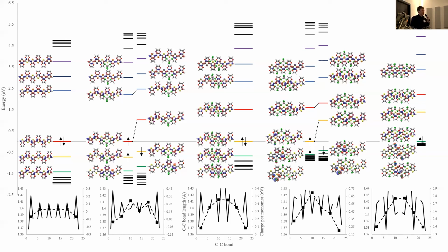Now, when you introduce the anion, it does indeed introduce an anti-bonding and a bonding state. But what this shows is that actually that's not driven by the anionic anti-bonding bonding state. In fact, these happen up here and down here, and I'll show you that on the next slide as the last slide of the presentation. What you're actually getting is that as you remove an electron, it actually bumps up this now unoccupied state into the gap, creating the sense of a new state without it actually being a new state. As you remove the second electron, it bumps the level wholesale up into the gap, and this process is repeated the more electrons you remove.